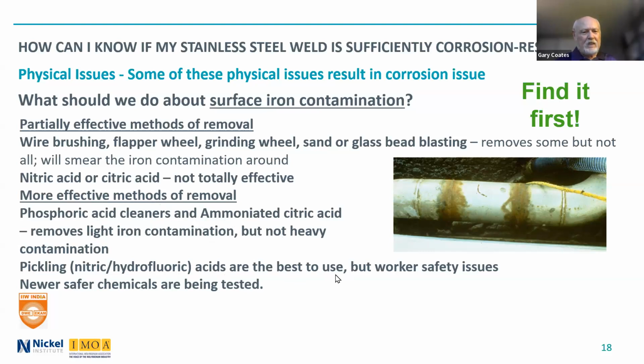And despite the fact that pickling, whether pickling liquids or pastes, is very hazardous, you need special equipment for the workers, they are really the best ones to use. They're nitric hydrofluoric acid-based chemicals. There's some newer, safer chemicals being tested now. A friend of mine is working on that now, just testing somebody's formulation. And we see that it works reasonably well on light iron contamination on 304, 316, but we're looking at it on other materials also, like the higher alloyed stainless steels.